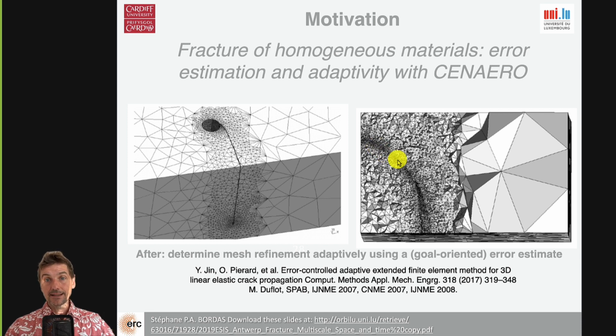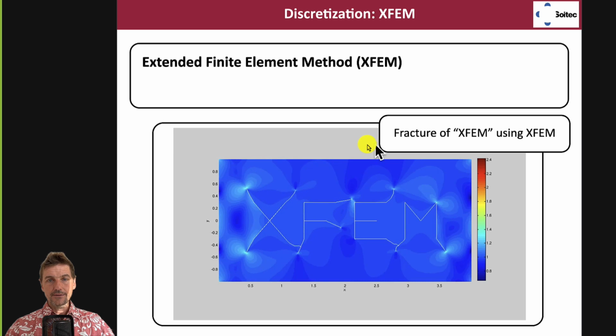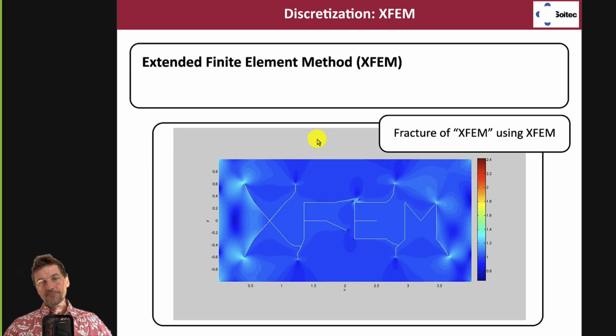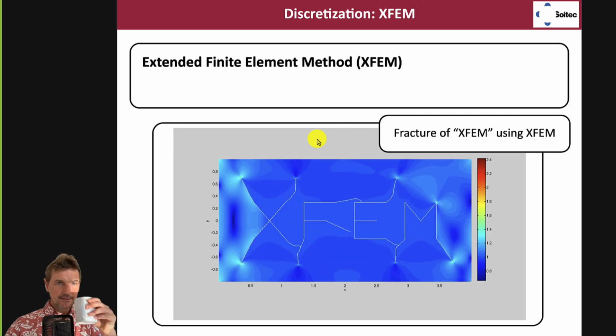We saw at the time that if the stress intensity factor is computed slightly off, the whole crack propagation path can be wrong, because each increment will be off and you cannot heal the crack. Once you've made a mistake in the propagation, you have a history-dependent simulation which cannot be cured. So this is very important. Think about error estimation and adaptivity with a goal in mind, as opposed to doing simply adaptivity using the energy as a target.